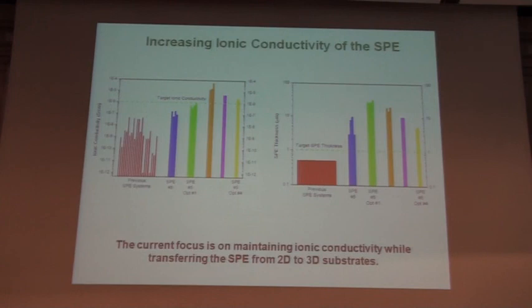Okay, so in terms of the polymer, what we do is we set targets for ourselves that are associated with stage gates. Again, very different from the kind of academic research I'm used to, where my students really work on understanding how things work, and sometimes the timelines we don't really pay that much attention to. In the company, we have pretty strict timelines because we've promised to meet certain milestones for our partners and for our investors. So we use our model that we use to calculate what the power density and energy density should be, and we set these lines for the physical properties we need to meet. So in this case, ionic conductivity for our polymer, to achieve a 5x power density improvement, we need to hit about 10 to the minus 6 Siemens per centimeter. And then in thickness, we need to be at 1 micron. We've gone through many systems that did not work very well.